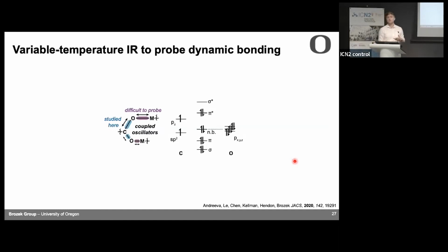And when you're studying bonds, you often think about vibrational spectroscopy, IR, Raman. And the problem is that metal carboxylate bonds are really, really low frequency bonds. And my thinking was, I figured if you heat these up, you should see more of that unbound state. So we needed to be able to do variable temperature spectroscopy, and we needed to be able to see bonds that were really low frequency. Well, in my lab, we can't do variable temperature Raman or variable temperature terahertz. The best thing we can do is variable temperature IR. And by variable temperature IR, it's much easier to see the CO bond. Now, I figured that even though we're not looking at the metal oxygen bond, we should be able to see changes in the CO bond.